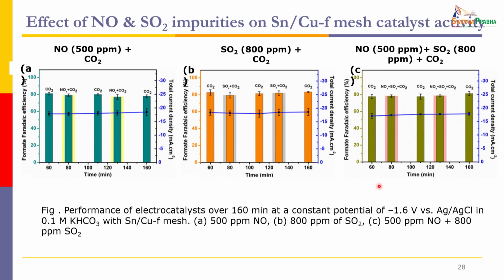saturate with NOx, and then perform the experiment. Then again, when the reduction is complete, you again pass carbon dioxide, do the experiment, then again pass NOx. Every half an hour we change, like you introduce NOx and you do not introduce NOx. So if you look at the performance, this is for the tin catalyst which is deposited on the copper foam. There is no change in the Faraday efficiency.